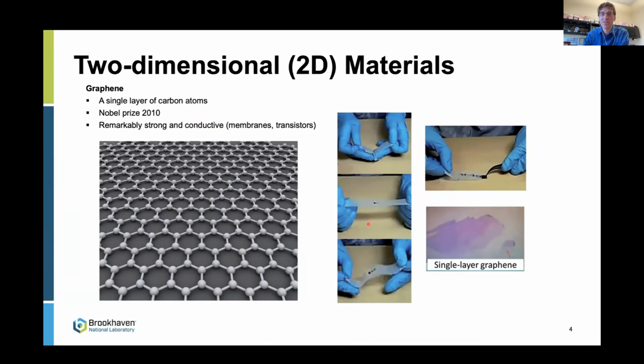And what I'm showing here is the state of the art of how people actually make 2D materials in most labs. And it's literally with Scotch tape. You take off-the-shelf commercially available adhesive tape, and you sprinkle some graphite crystals on it, and you press the tape into itself repeatedly. In doing that, you fracture apart these graphite flakes over and over. And if you do that enough times, you might get lucky. In some areas, you're going to get graphite stacks that are quite thin, maybe even just a monolayer thin. And so then you can take this Scotch tape and put it against a substrate, like a piece of silicon wafer, and rub it.